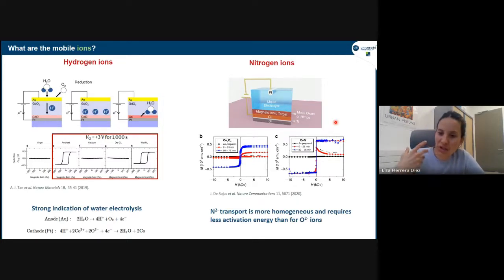What they extract from this is very interesting, because they can show that with nitrogen ions the process seems to be more ordered, more homogeneous. They get a more ordered front of nitration inside the layer, which could be important to reduce defects in the system, for example. And they could also show that the energy barriers to move nitrogen are not as high as in the case of oxygen, which could be an outlook towards even lower energy and lower voltage operation for these devices.